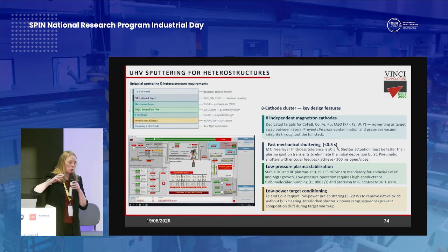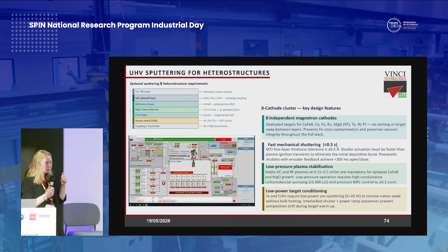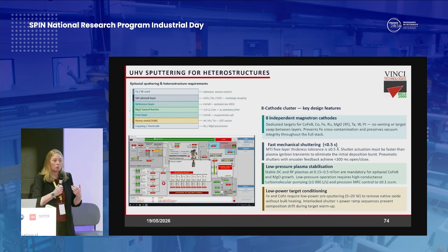I think there's an important role of using sputtering systems for the non-critical layers in the growth of certain of these power devices and 2D structures, heterostructures, because using sputtering to do epitaxial growth means that there are certain design features that we incorporate from the beginning, such as being able to grow atom by atom over a very long period of time, several hours, means that you have to maintain vacuum pressure extremely stable.